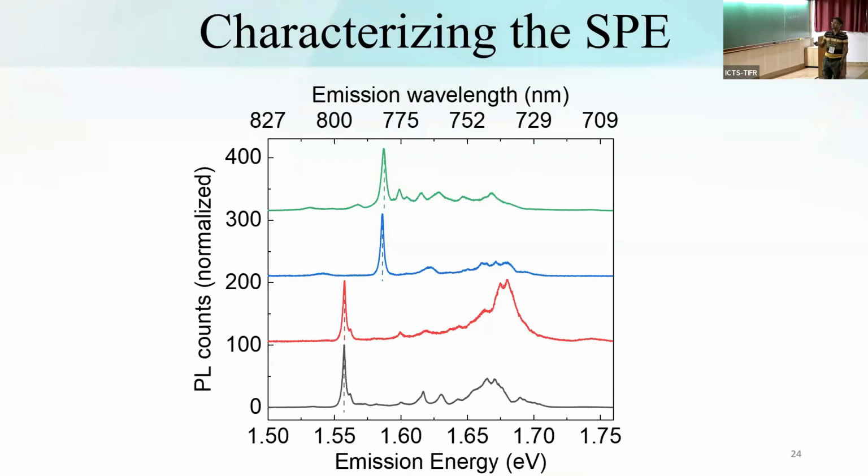Okay, so these are the spectral features that I was talking about. You see the exciton, which you hardly see, this is the free exciton. It's about 1.75 electron volt at low temperature. And this is, by the way, a 4 Kelvin or so measurement. These are the sharp peaks that I'm talking about. This is about 200 meV below this. And these are different pillars.